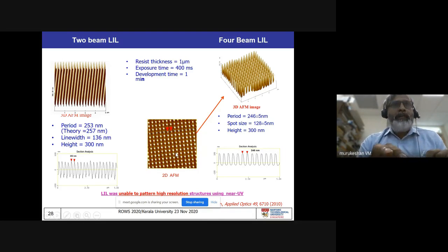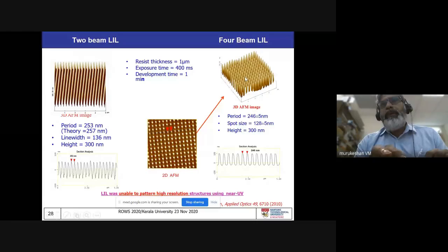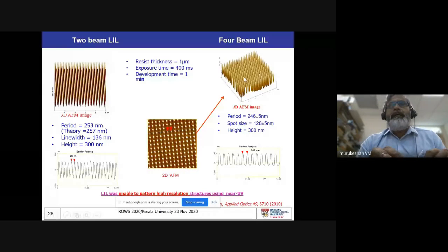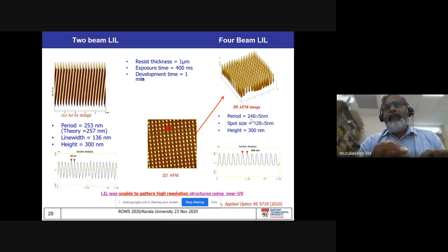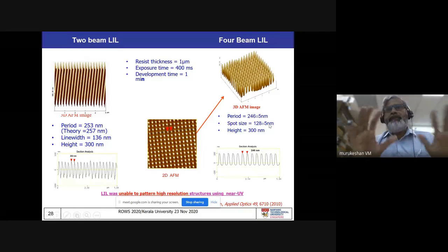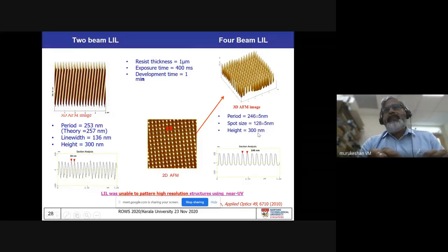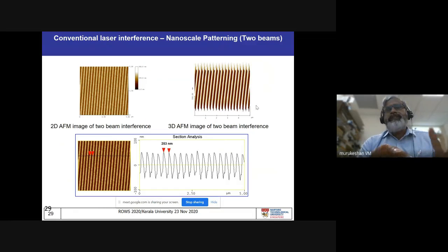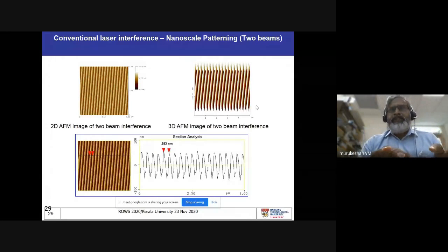These are all images taken using atomic force microscope, and you can see that these are very, very nicely patterned features. And this has got a period of 240 plus minus 5 nanometers, with a spot size of about 128 plus minus 5 nanometers, with a height of 300 nanometers. So these pillars are actually what we are really looking at. The line features such as grating, and the contact pillars such as this. And you can see that we are still somewhere around this 100 plus nanometer size.